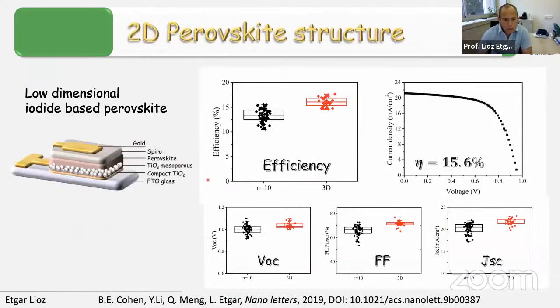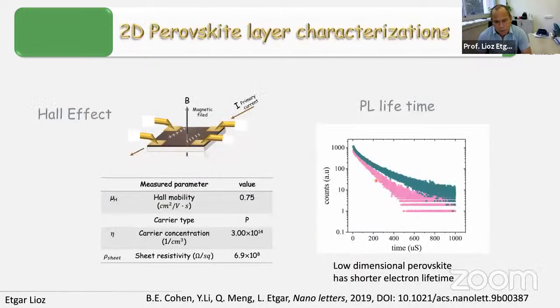So when we implement this into devices, indeed, at a very low N value, which means almost a two-dimensional material, we can create nice devices with more than 15% efficiency, which is quite amazing since so far when you reduce the dimensionality of the perovskite, you increase stability, but on the other hand, the conductivity through the layers is really bad. And in this case, you can see here nicely that it didn't harm the performance. And then we started to do some characterization, like Hall effect measurements, which can estimate the Hall mobility. And this is more or less the Hall mobility of those perovskites, around 1. It's much lower than silicon on one side, but on the other hand, it's much higher than the organic materials. So it's really something in the middle, which still permits some good conductivity in those layers.